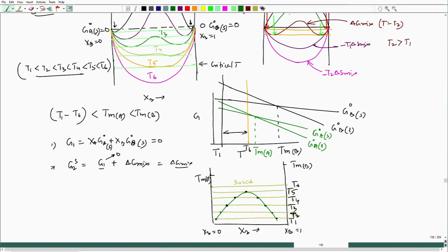When we have such a situation, as we go to lower and lower temperature, the gap between these two compositions extends, so they would become more preferably phase separated. As we go higher and higher temperature, the phase separation will go off slowly, and at one particular critical temperature the phase separation will go off, and everything would be a single phase solid solution. Here we are taking solid solutions. So, when this kind of situation appears, it is called a phase separated phase diagram.